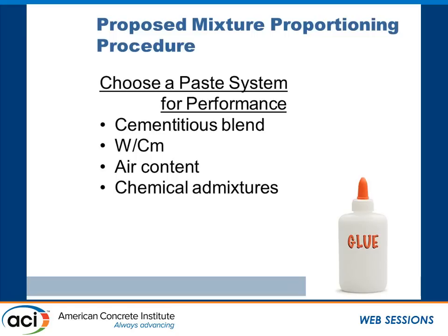Okay. How much air do you need? Again, we've done a little bit of work trying to make sure that the recommendations developed in 1952 by Klieger were great for type 1 cement, no admixtures, no supplementaries. Does that rule still apply? Actually, it does, remarkably. It's still pretty good that we want about 5 to 6% air behind the paver.